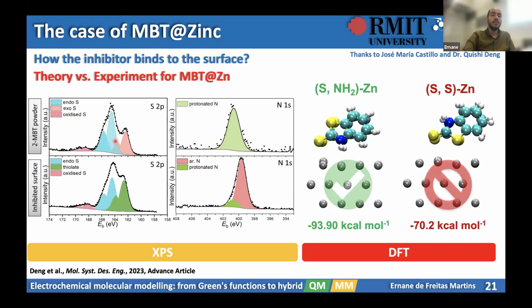So with the XPS, you can compare the case of the molecule before you adsorb it on the surface and also after adsorption. And you can compare this with the molecular modeling. In the molecular modeling, what Jose Maria did was to check, for example, two different cases of self-assembled monolayers, where the nitrogen from the molecule is interacting with the surface and where the nitrogen is not directly interacting with the surface. Jose computed adsorption energies. This one is more stable, so it looks like this one will be predominant, the one with nitrogen pointing to the surface.